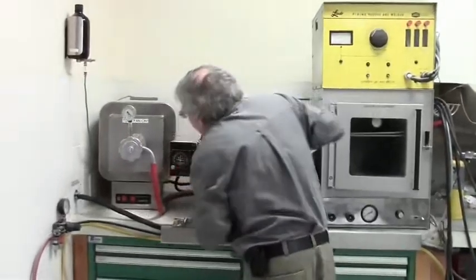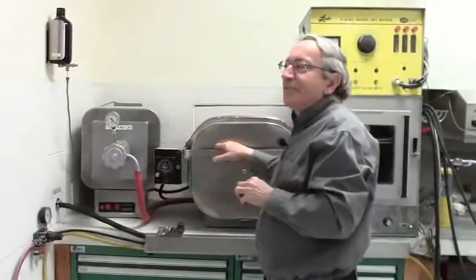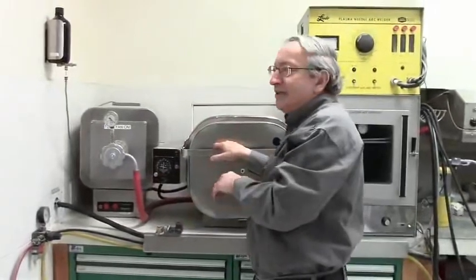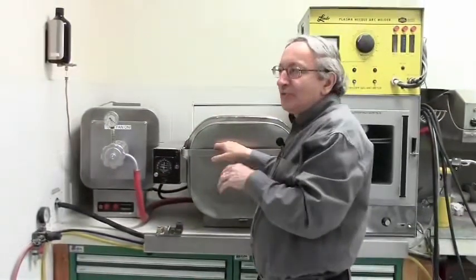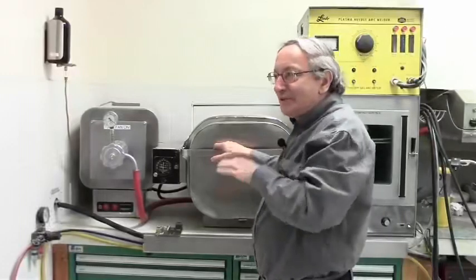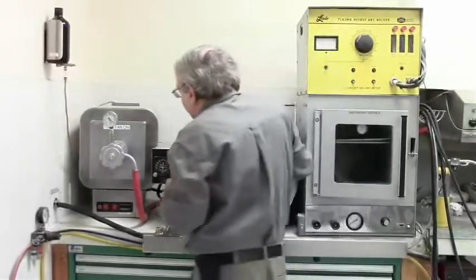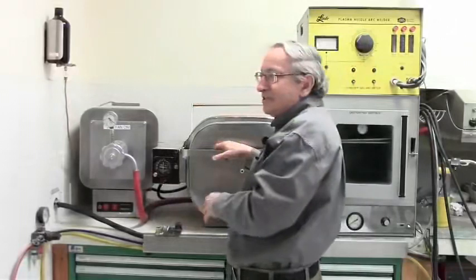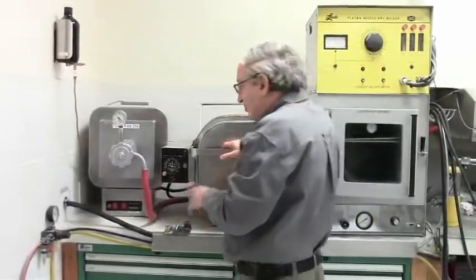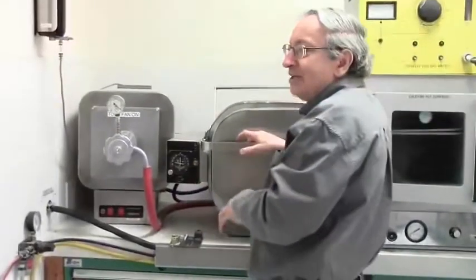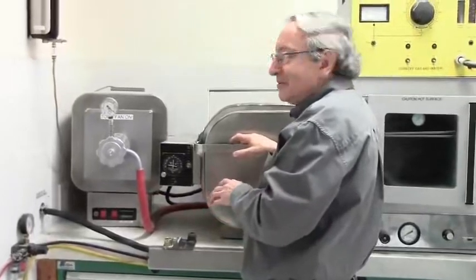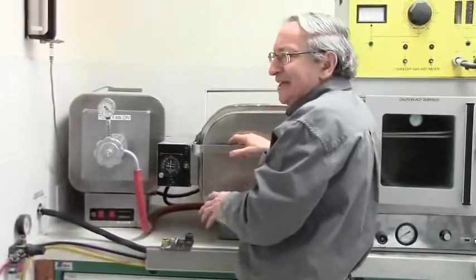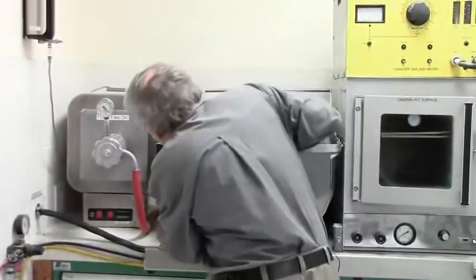The temperature has to be about 100 degrees above the melting point of the braze alloy, because you want, A, to be sure it melts, and B, it has to be very liquid. You want it to flow beautifully. But if it's too high, it just causes needless oxidation. So you look up the melting point of the alloy and add anywhere from 50 to 100 degrees. So this, I believe, melts at about 680 C. So I'm setting it for 750 C.